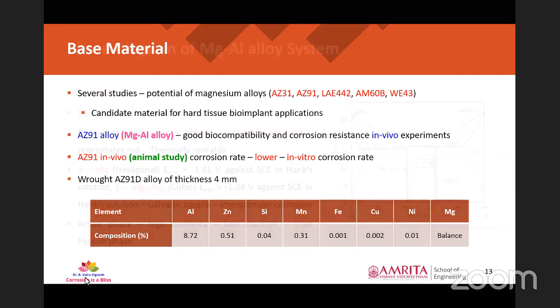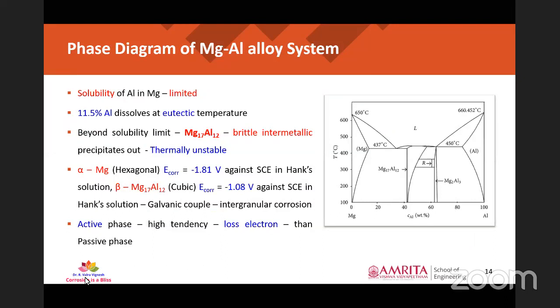Let us see the phases present in this magnesium aluminum alloy system so that we can conclude how it could be done, or what parameters we should consider while we fabricate magnesium aluminum based systems for surface composites. The first thing is that the solubility of aluminum in magnesium is very limited, and we can see from the phase diagram that only 11.5% of aluminum dissolves at eutectic temperature. Beyond this solubility limit, Mg17Al12, a brittle intermetallic, precipitates out of the alloy, and that is thermally unstable too.